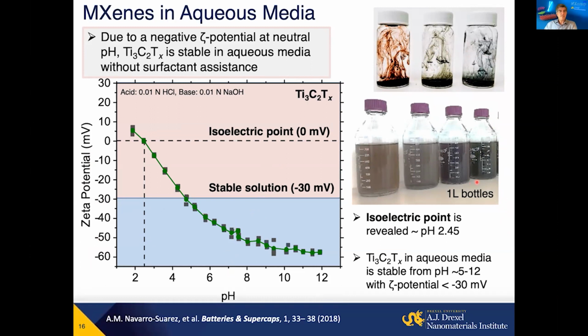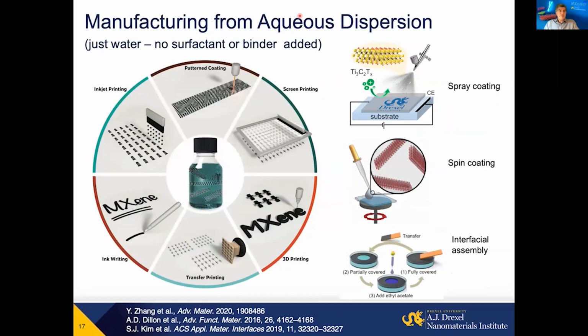And as soon as you have a solution, colloidal solution, or liquid crystalline solution that we used to make, for example, the film shown in a previous slide, you can process them from aqueous dispersion. Moreover, again, let me repeat, no surfactant or binder needed. So we have an environmentally friendly and very easy process, and we don't have to burn off binder and surfactant, unlike in the case of using metallic particles here. And that can be inkjet printed, screen printed. We can write, just fill your pen with MXene, or of course do 2D or 3D printing here.